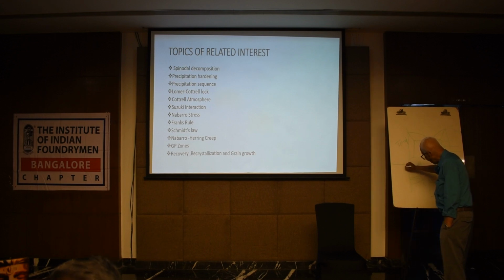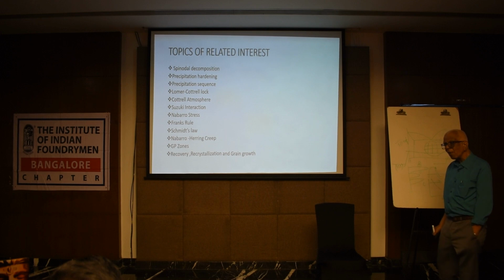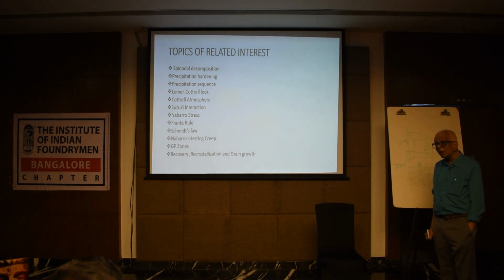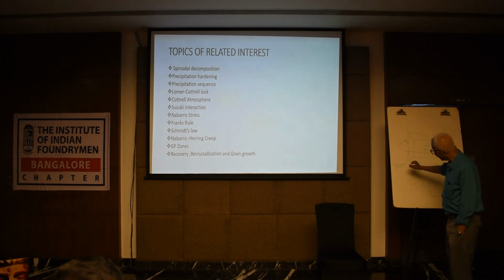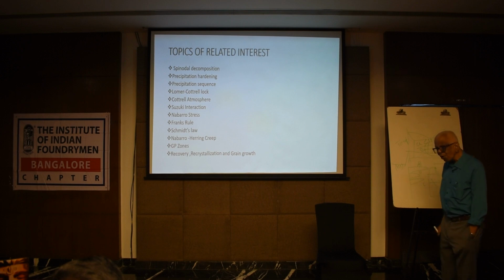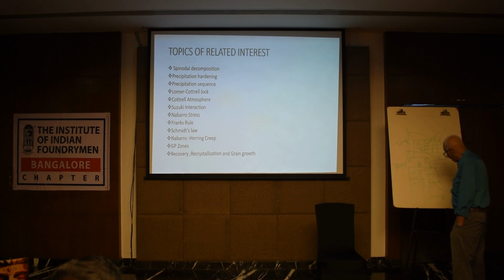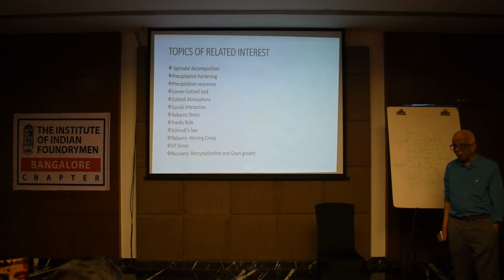If you have slip planes, the intersecting slip plane is {111} in aluminum. 111 is the Miller indices of a slip plane in aluminum. And there is what is known as a unit dislocation. The unit dislocation is given by a/2 <110>. That's a unit dislocation. But unit dislocations don't exist as such. They separate themselves into partials. They're called Shockley partials, given by a/6 <112>, or <211> or whatever. That is the Burgers vector of the dislocation.